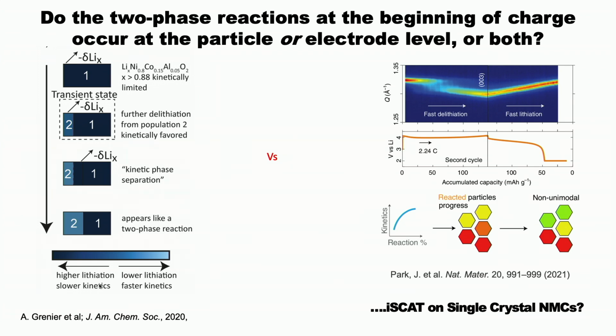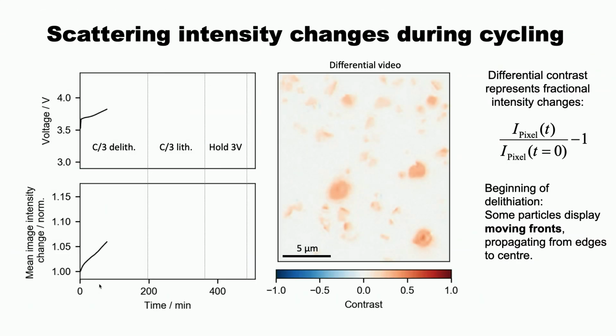And the question I want to talk about was, again, this discovery, at least from our hands, that if you started to pull lithium out of these materials, even though these materials in principle were a solid solution, they also had these two-phase reactions. And we said that this was associated with particle-level phenomena. Meanwhile, there's a very nice paper by Will Chu's group and Martin Bazant, who commented on the fact that there was probably an electrode-level process that caused this. And so we wanted to look at this phenomenon by our iSCAT method to see if we could at least look at it at the particle level.